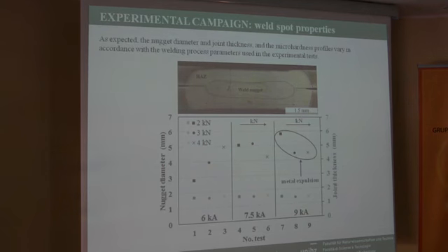Here you can see an overview about the dimensions of the weld nugget, in particular considering the diameter of this region and the thickness of the weld spots. These are two geometrical features that are important to evaluate the quality of this typology of welding process. Obviously, we have a variation of the nugget diameter and of joint thickness according to the process parameters that were used during the tests.